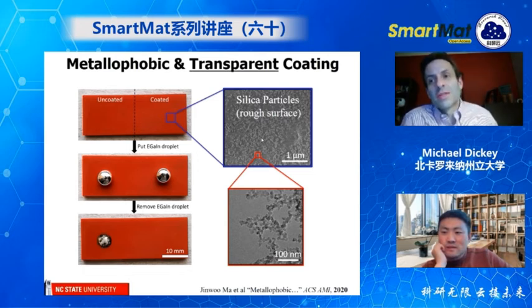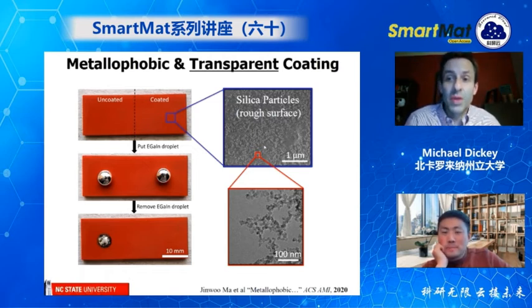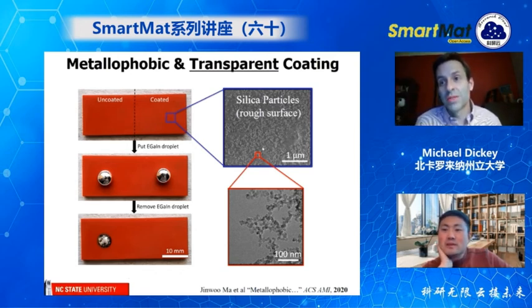One thing that's interesting that's different is that for this surface, the chemical composition doesn't matter. We can make this fluorinated, super hydrophobic, and it works. But we can also make it hydrophilic. We can make it with hydroxyl groups, and water will wet it, perfectly wet it. But the liquid metal doesn't stick. So it's really the roughness and not the chemical composition of the surface that seems to matter the most.